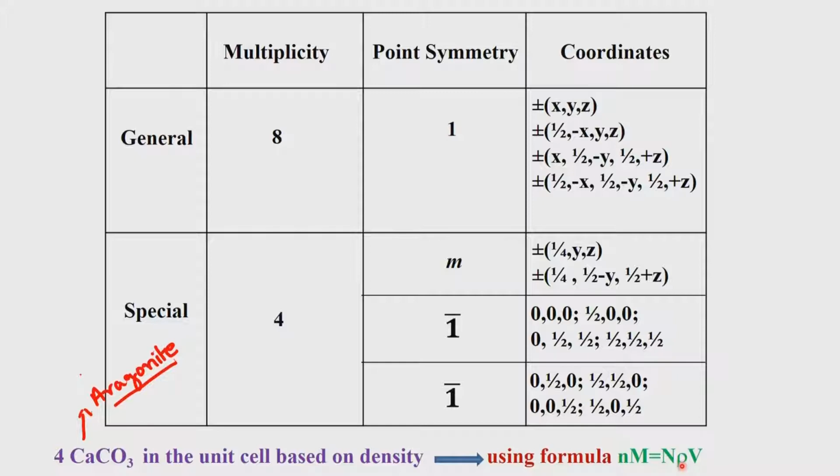There is always a possibility of going wrong in this assumption, because the software gives the density of the crystal based on the value of n. Suppose, let us say in this example n was assumed to be 8, then we will get a wrong density, because we know that n is equal to 4 by experimental determination of the density.